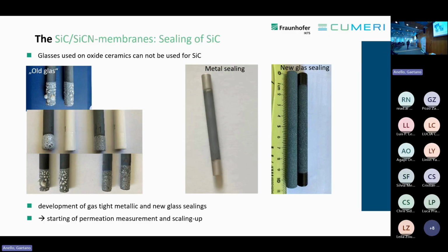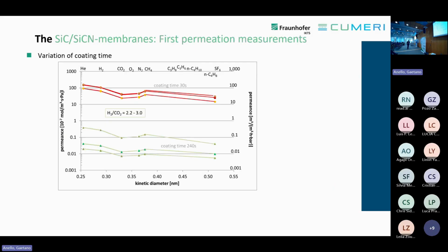Now we had, for the first time, membranes for doing permeation measurements, and we are also able to scale up. I show you as a nearly last slide the very first results of permeation measurements. This result is not great. As you can easily see, here is an example of variation of the coating time. When we are coating quite short, we have dramatically high permeances in the range of 100 cubic meters per square meter per hour per bar.